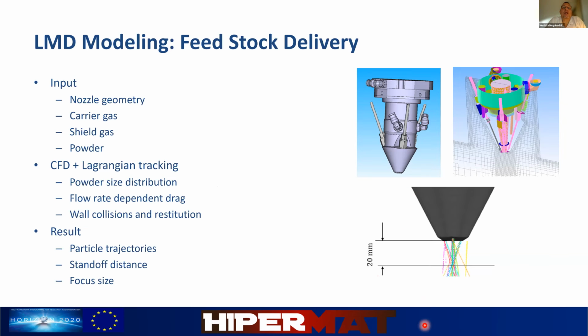So the LMD process presented by Sergio, we attempt to model it in the same sequence as the process performs. So we first have to deliver the feedstock to the model, and that implies we have to resolve the delivery nozzle and the flow fields inside these nozzles. So we represent the nozzle using a computational grid as shown on the right-hand side. The grid has different solid domains, where nothing flows through, and several fluid domains. Those are the ones where we define the carrier gas flow, that is the gas that is carrying the powder to the delivery point, and shield gas, which will shield the processed area from oxidants or other impurities.